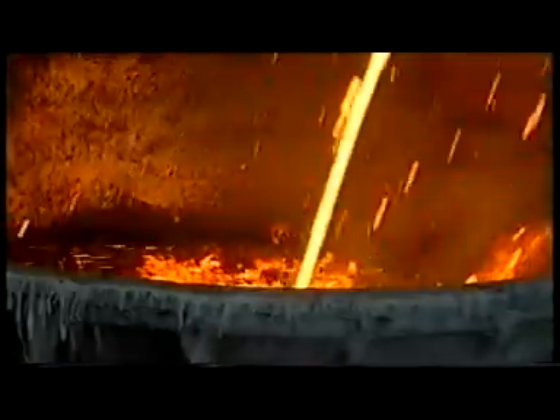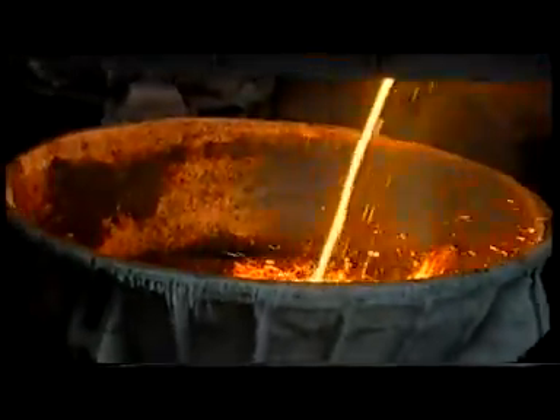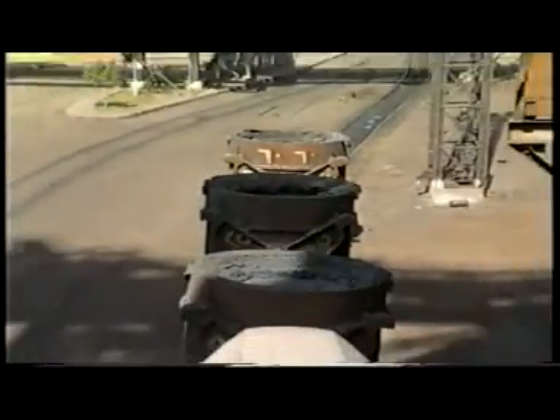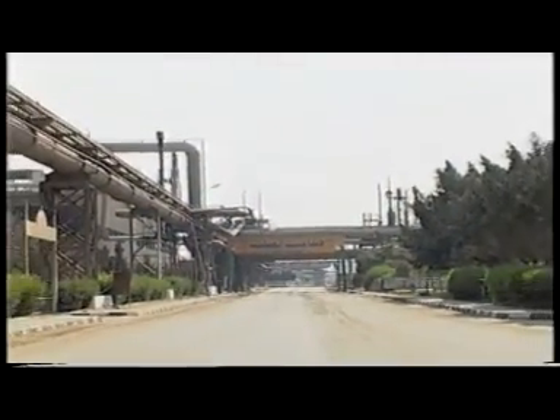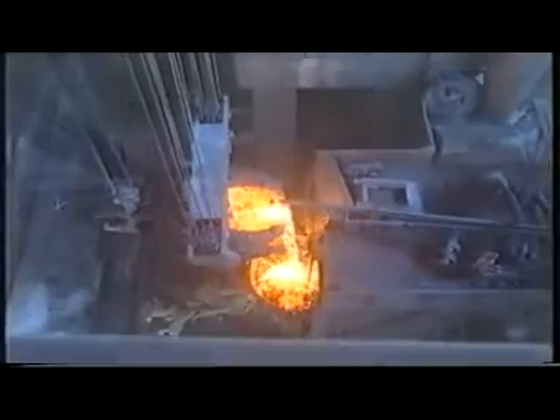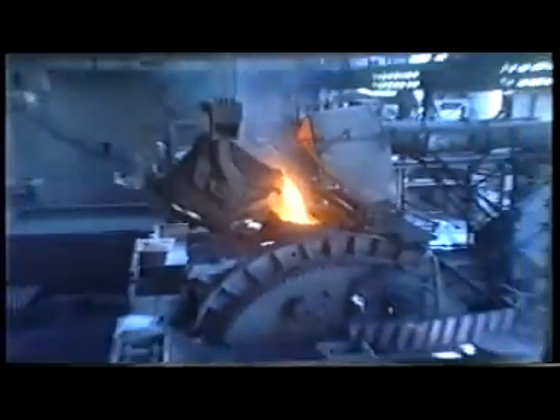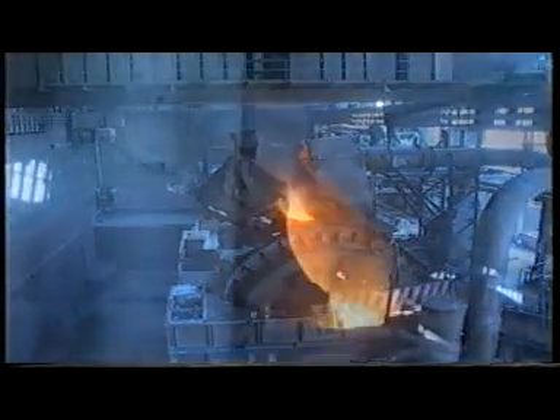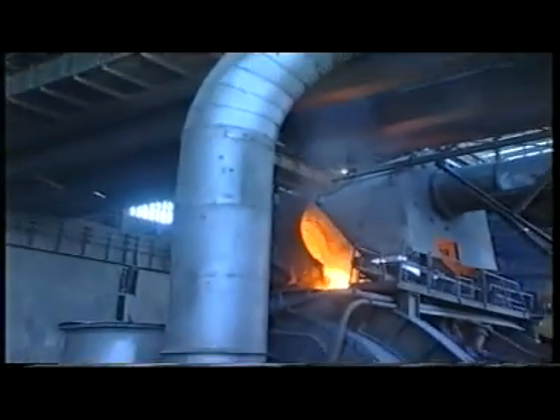The molten pig iron is poured inside ladles, each with capacity of 70 tons, carried up by special wagon railroad to steel producing facilities where the molten pig iron ladles is discharged inside 2 big mixers, each of 1,300 tons capacity, which maintain the heat of pig iron and achieves its homogeneous analysis, before charging in the oxygen converters which convert pig iron into liquid steel.